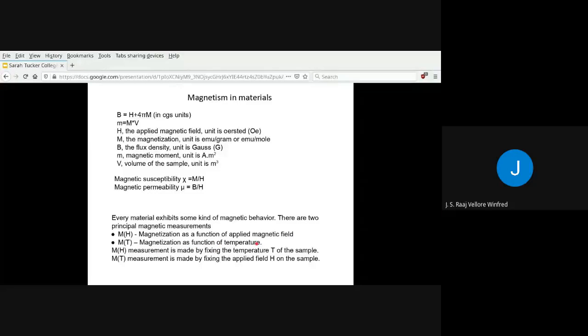These two measurements are done in a SQUID magnetometer by first fixing the temperature of the sample and applying the magnetic field to get M as a function of H, and then fixing the magnetic field, excuse me, and varying the temperature and studying the magnetization of the sample.